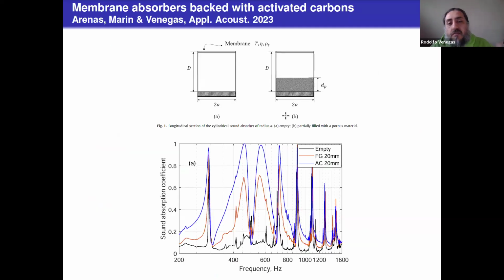We have also applied similar ideas, but for the case of membrane resonators. This has been recently published. Here in blue, we have a membrane resonator backed with some activated carbons, and in red we have the same configuration, but instead of activated carbon, we use a conventional foam. And in black is the empty cavity, so we have pretty much no absorption, but absorption can be greatly enhanced by the use of granular materials like activated carbons.